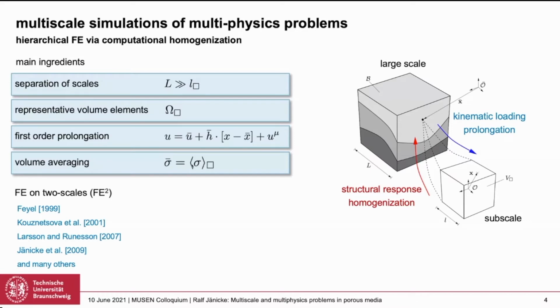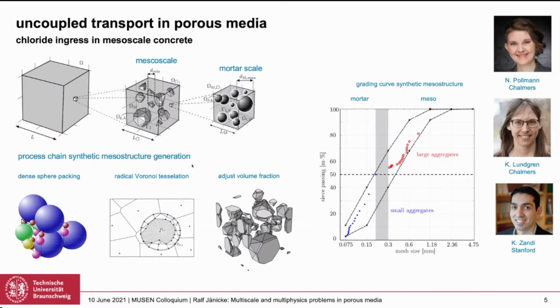And now the thing is that we can apply that to multiple different problems. And just to show you how it looks in action, I would like to directly go to the first case, which has been part of the PhD thesis of Nele Pollmann at Chalmers, together with colleagues there, Karin Lundgren and Kamyab Zandi. He's now at Stanford. And the problem here is chloride ingress in mesoscale concrete. So that means we have cement paste with very small particles, which together gives the mortar, and then you have larger particles or larger aggregates, basically.